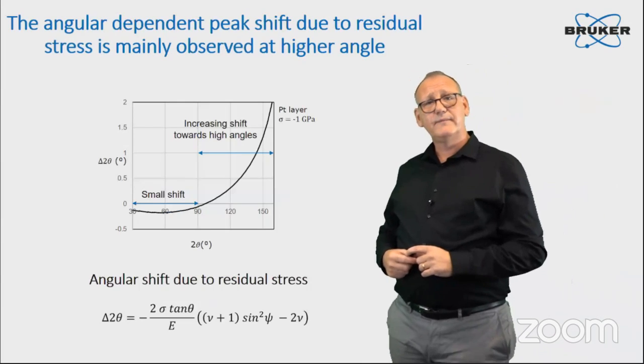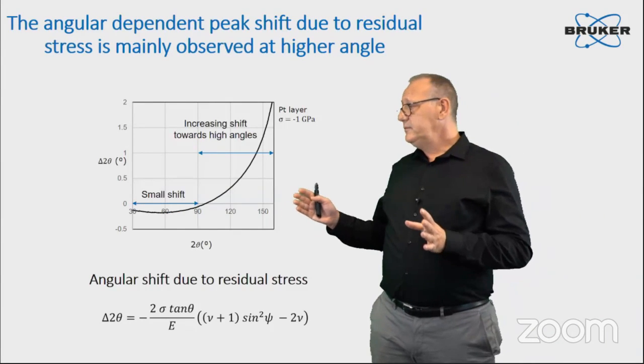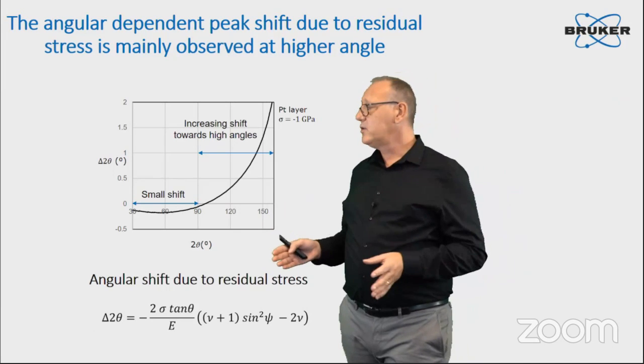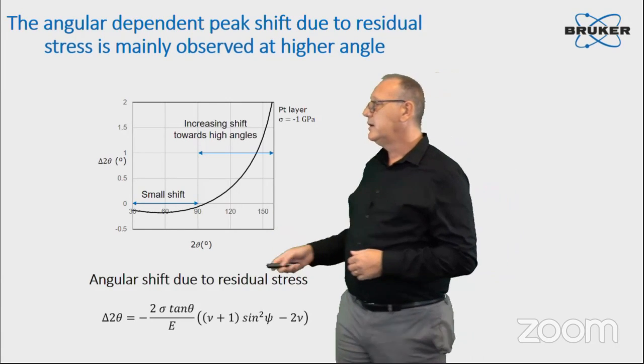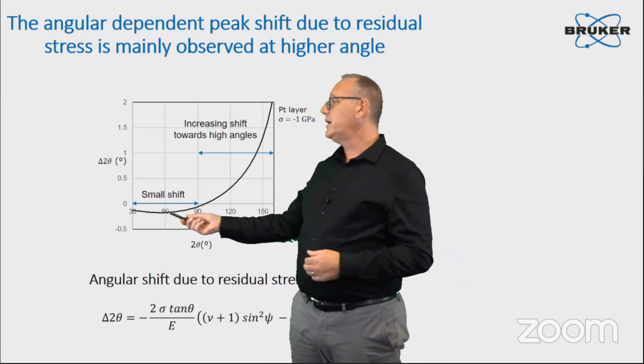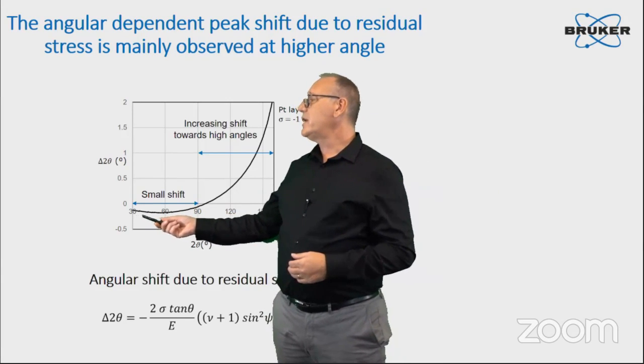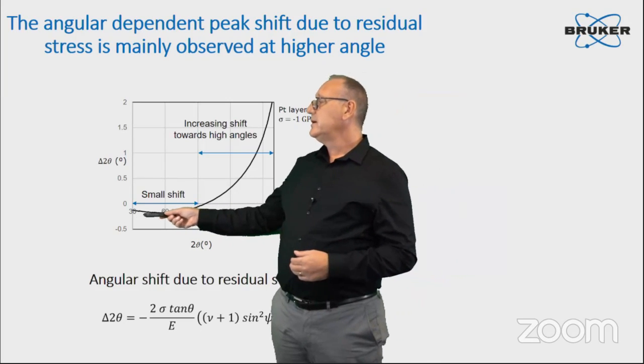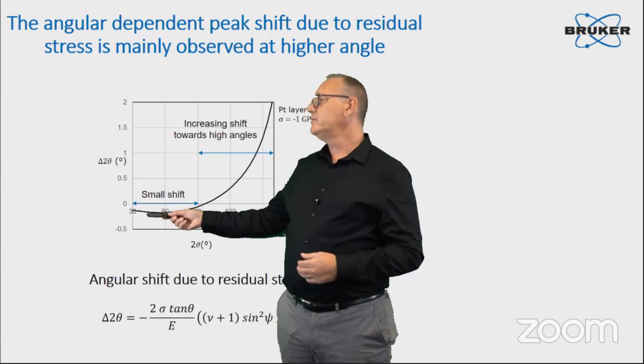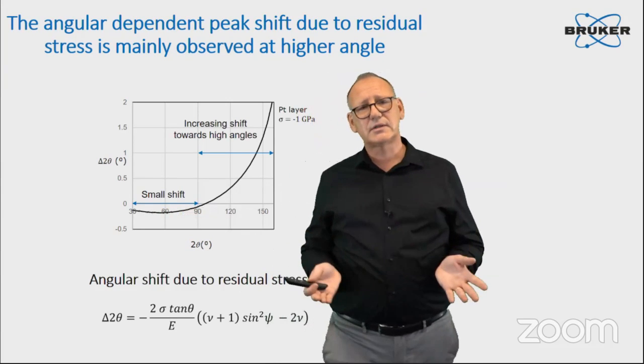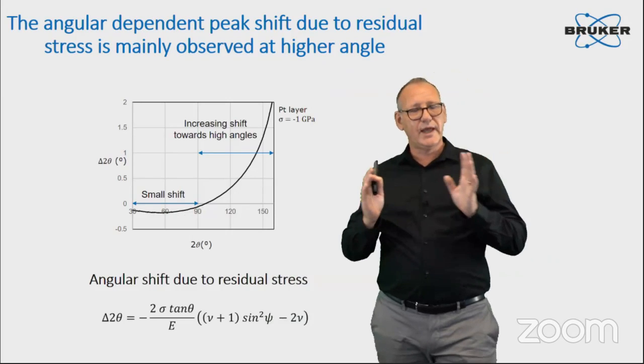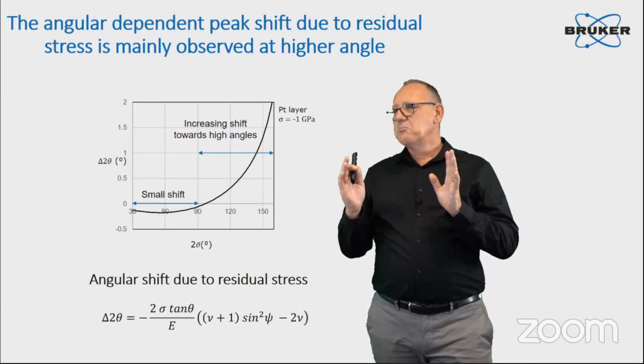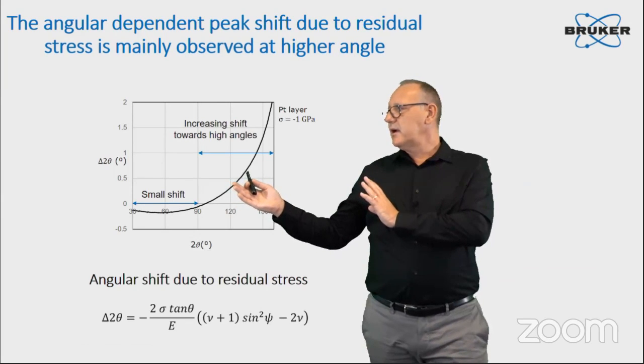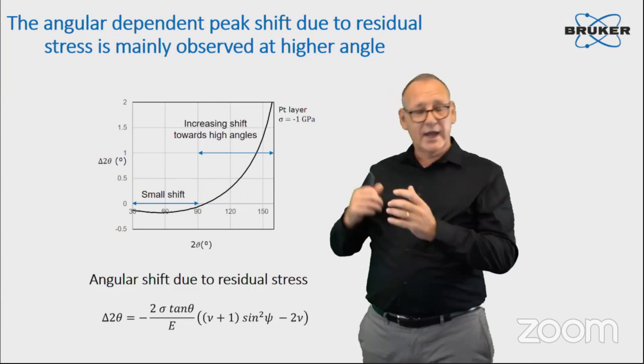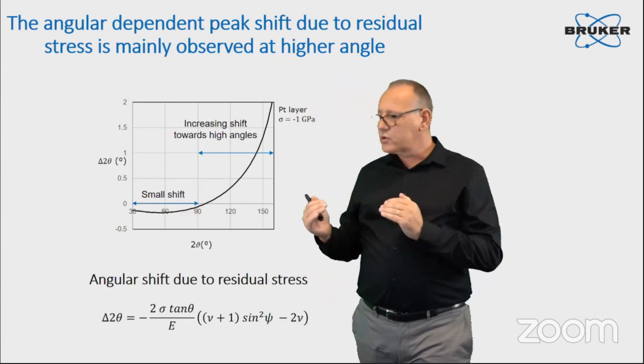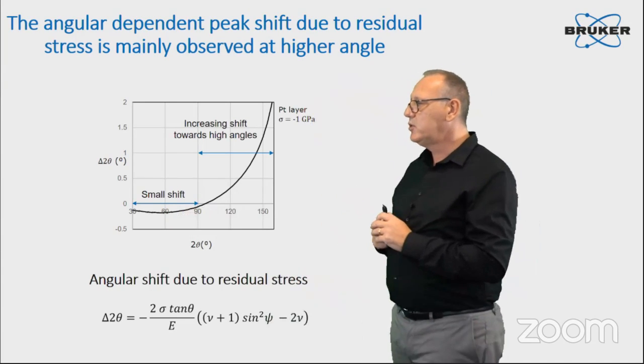As I said just before, the high angle range is crucial to identify and evaluate accurately the residual stress in your material. If you would simply measure from 30 to 90 degrees, the shift due to residual stress is lower, and we could even think almost constant. It's not really constant, but you remember the small peak shift we had on our low scanning range, maybe can be attributed to this effect together with the refraction effect. But since it's almost a constant effect at low angle, we were not really able to understand it.